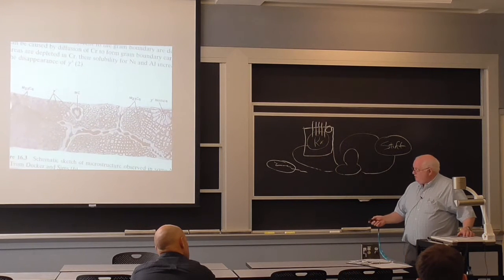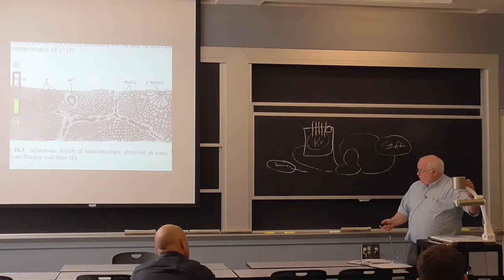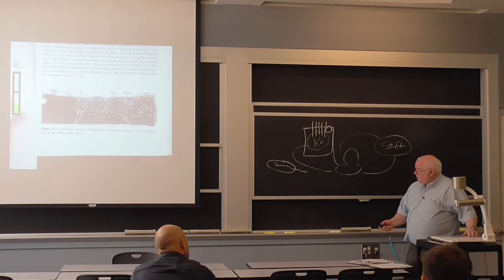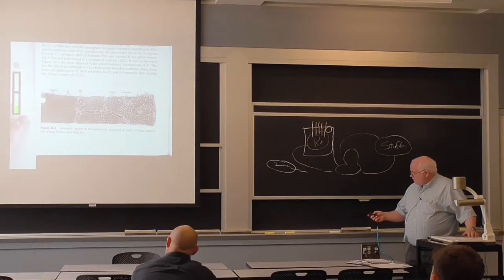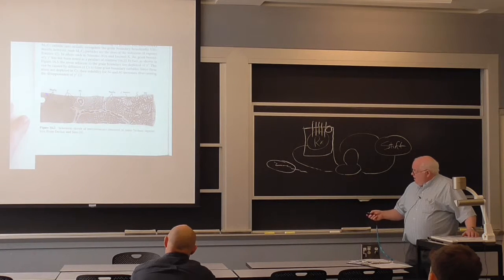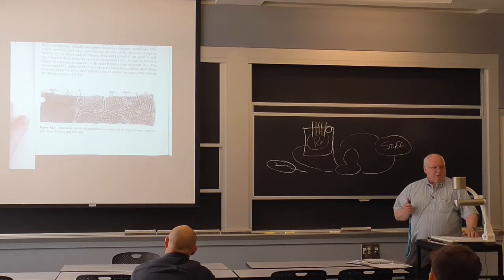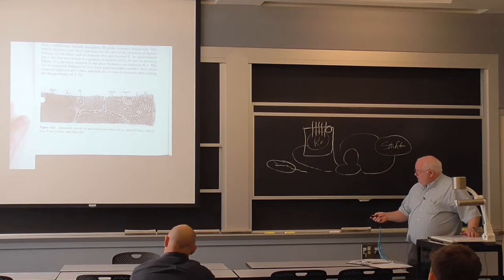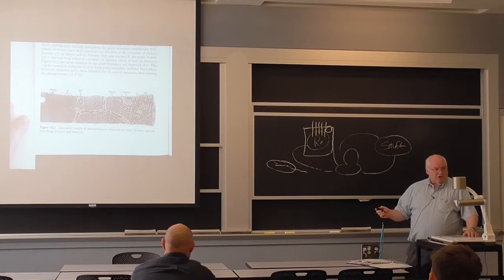So the other thing about the nickel-based alloy, this actually is out of one of Lippold's books, but he stole it from somebody else, Decker and Sims, who wrote a book on nickel-based superalloys before him. And this is not a weld. In fact, this is an artist's conception of a microstructure, okay? This would be increasing aluminum or titanium. And here you have nearly pure nickel, and over here you have a nickel-based superalloy that's going to go in a jet engine turbine blade.